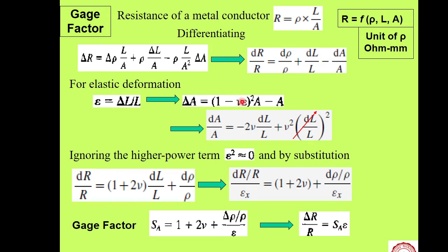If this is square, area is say A into A, or if it is circular, this is pi by 4 into d squared. Then due to this strain field, what is the strain in transverse direction? Minus nu into epsilon. Nu is Poisson's ratio, right? That we know.